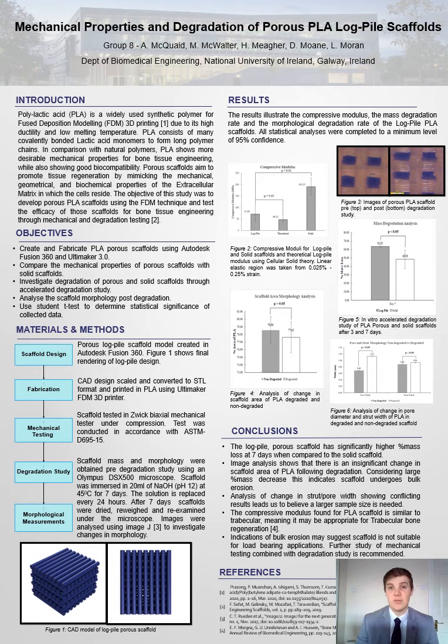For each test performed, a scaffold of solid PLA was used for control. Mechanical testing was performed using a biaxial Zwick mechanical tester. The accelerated degradation study was performed by immersing the scaffolds into NaOH solution at 45 degrees Celsius for a 7-day period.